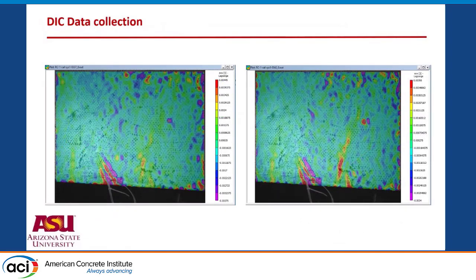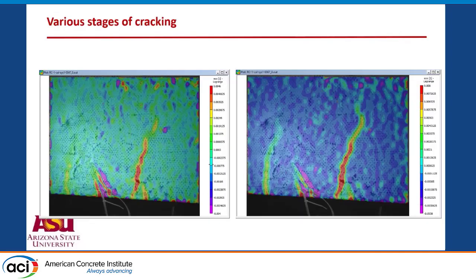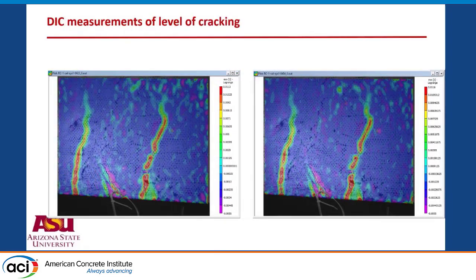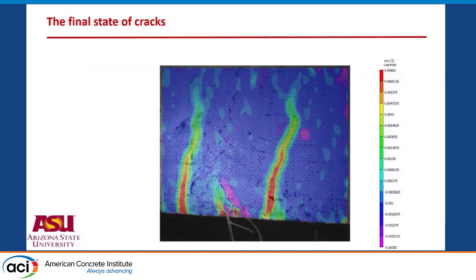DIC allows us to see how the system performs. We can see the initiation of one crack later become another crack, and you can see that the crack is about to evolve in here, and these are displacement and strain maps. Again, three cracks forming, so this is good because we have good reinforcement, and the reinforcement is causing the distribution of the load. As the cracks are opening up, the magnitude of the opening is so small. This is the needle in the haystack that the DIC equipment provides, helping us better understand and characterize the results.